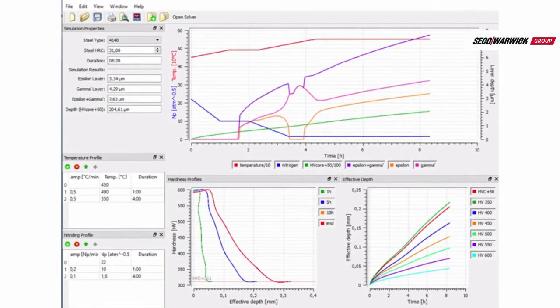the speed of growth and phase structure of the nitrided layer as functions of temperature, nitriding potential, and time. The simulator determines values of those parameters that will result in obtaining designated layers. In the offline simulator software, there's a possibility of setting process parameters by hand. Simulation results are presented as values of thickness of the nitrided layer, as well as graphs showing change of parameters and layer thickness throughout the process's time.